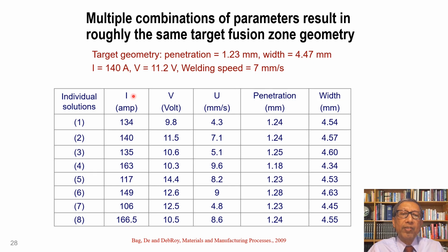If we look at the values, current varies between 106 ampere and 167 ampere. The voltage varies from 9.8 volt to about 14.4 volt, quite a bit of variation. And the scanning speed ranges from 4.3 to 9.6 millimeter per second. But all of these combinations provide the similar penetration and width, almost the same value that we wanted. So we tested the calculations by conducting experiments.